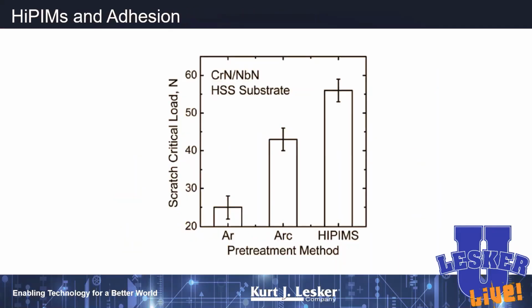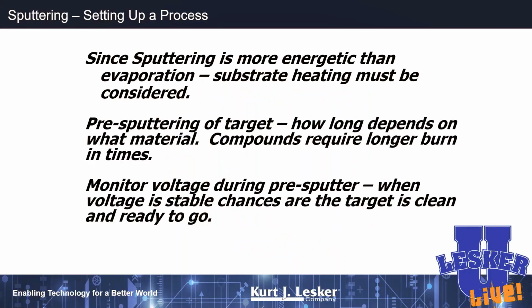So if we look at other film properties, things like scratch resistance, remember that cathodic arc has been the gold standard for scratch-resistant films. When you think about gun barrels, hip implants, things like that, which have to be amazingly scratch resistant, cathodic arc had been the gold standard. But now HiPIMS has demonstrated much improved scratch resistance over things like cathodic arc, because again, these arriving atoms are much more energetic. They form really nice, dense films. They're actually a lot smoother than what you would see with cathodic arc.